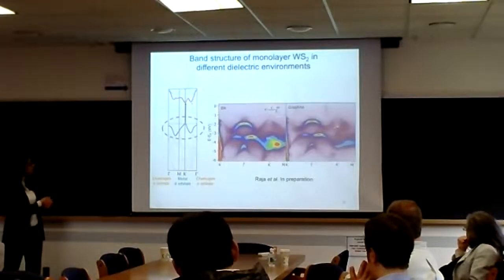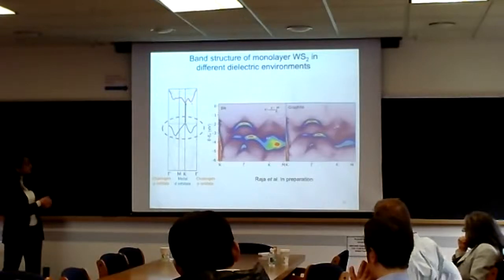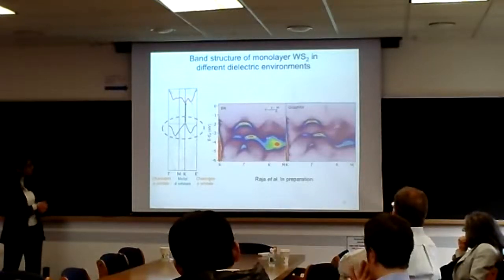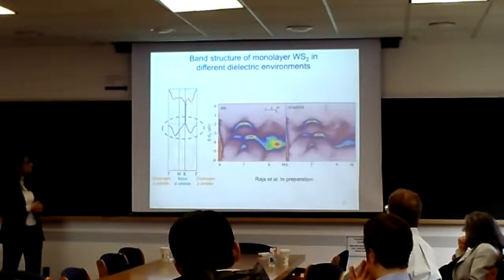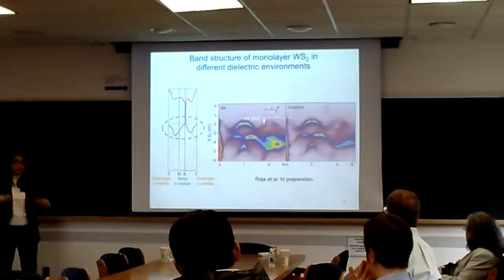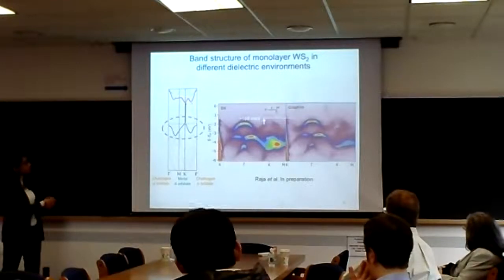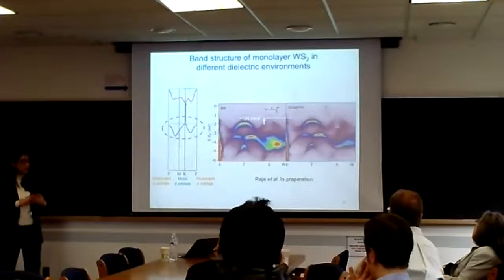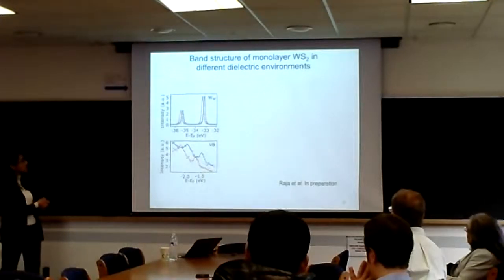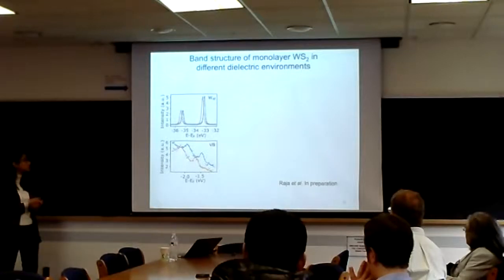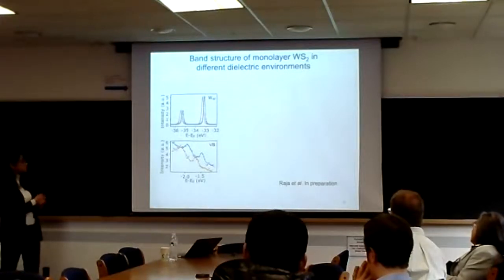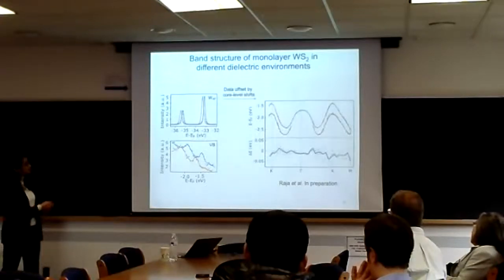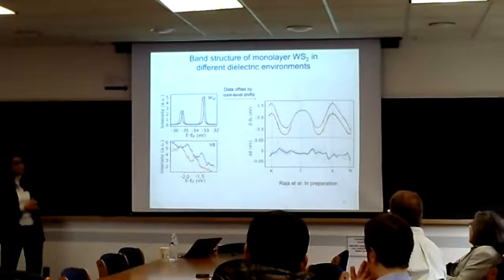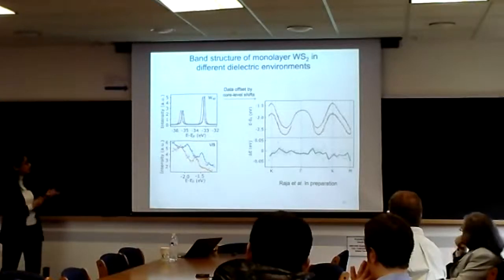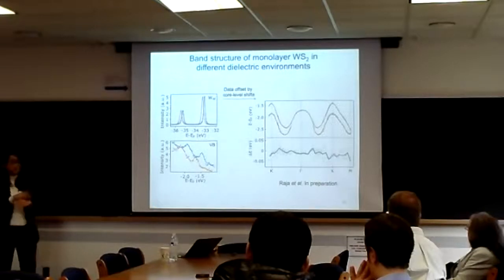This part of the spectra is related to the valence band, and the spin splitting that you see here is related to the K point, and this is the gamma point. Essentially, the primary effect here appears to be that you're just doing a scissor operator on your band structure, shifting your energy levels rigidly. In fact, if you calibrate your spectra with respect to your core photoemission, the tungsten 4f that's deep inside, you can overlay the two fits to the photoemission intensity, and within 10 meV you see that it's essentially unchanged.